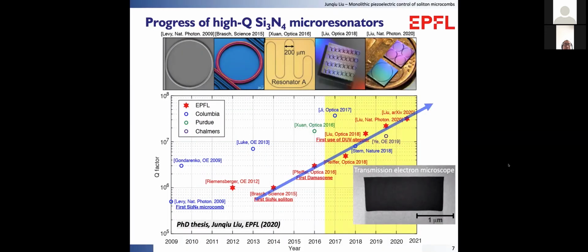To achieve such low loss, we have developed and optimized our Photonic Damascene process for several years. This chart shows our silicon nitride microresonators' Q improvement, corresponding to loss reduction, in comparison with the work from other groups. Today, we are able to routinely achieve more than 10 million quality factors of optical microresonators, which corresponds to a light propagation distance of a meter in nanophotonic integrated waveguides before the photon gets lost. This is only possible as a result of the entire silicon nitride community's decade of effort on the fabrication process.